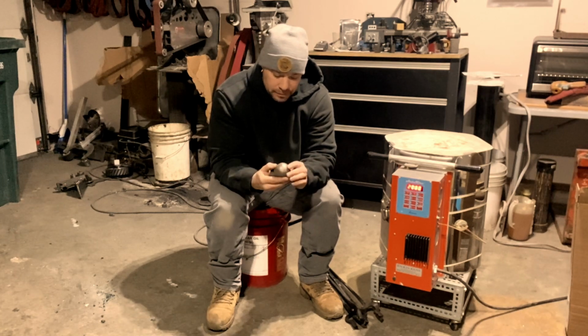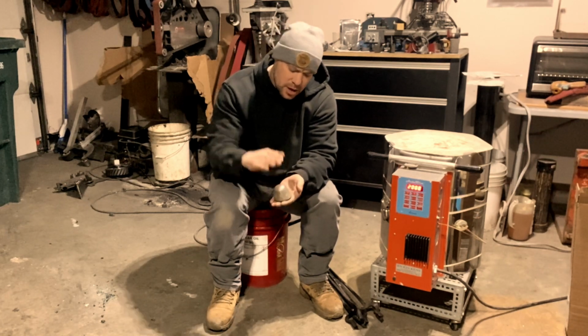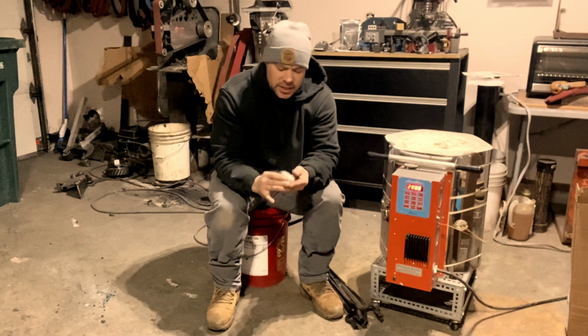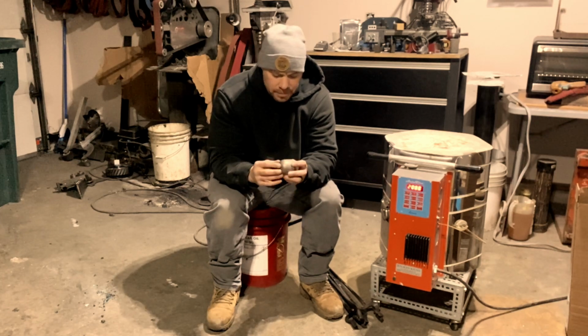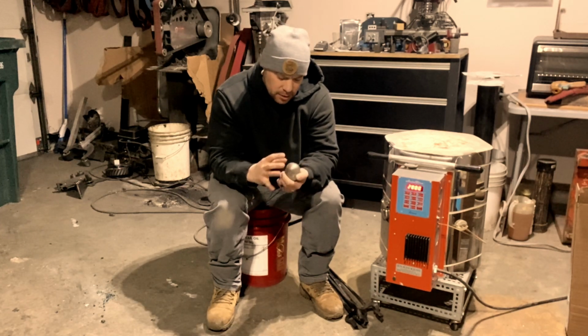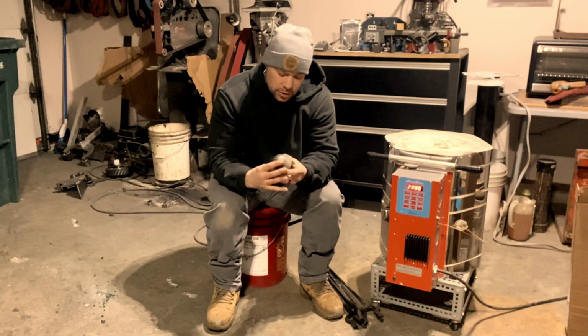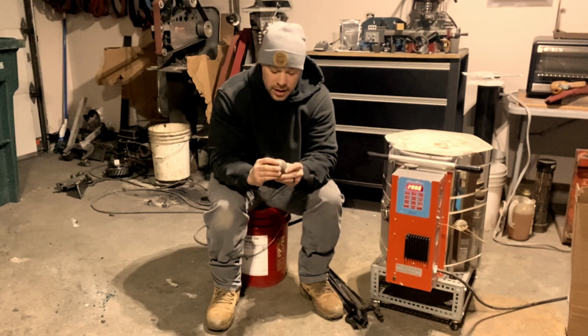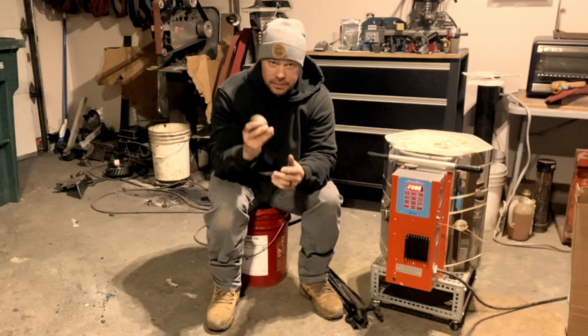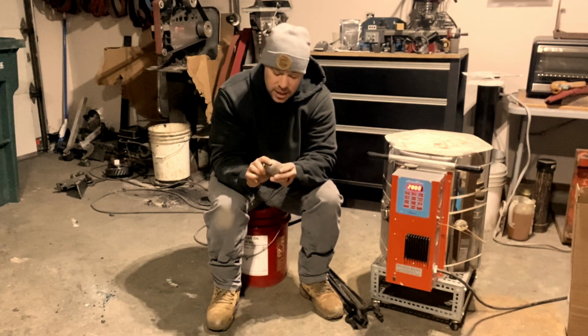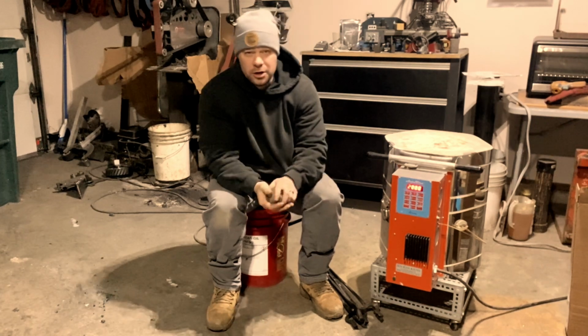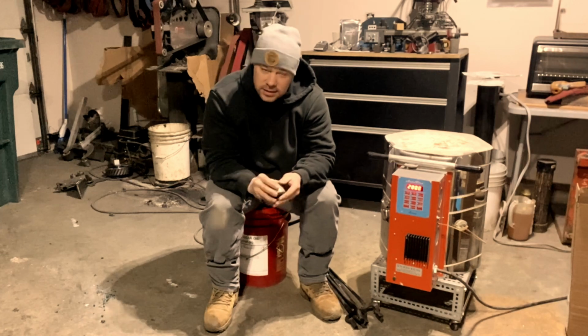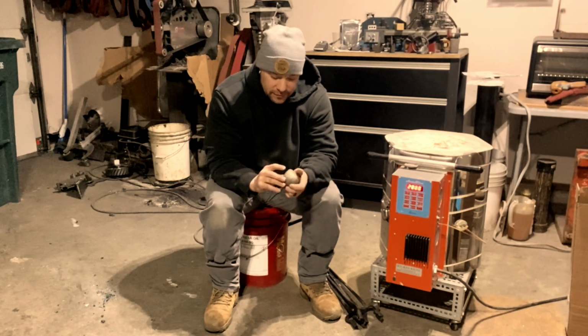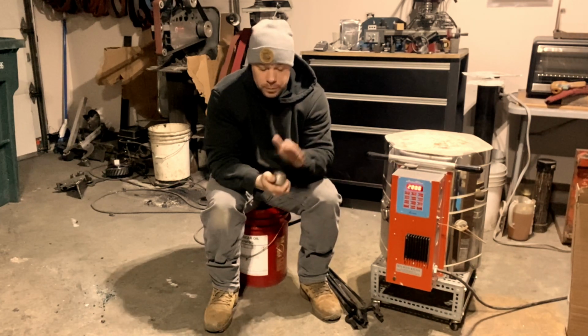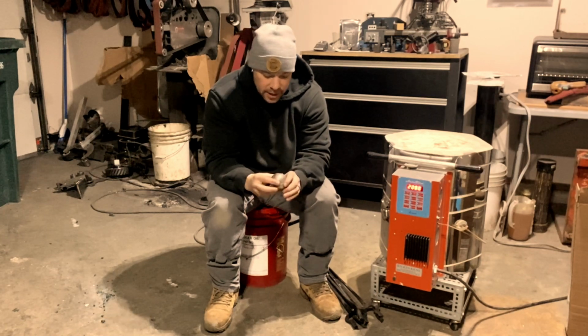And another reason you kind of want to press it down into a biscuit is because if there's any tiny porous holes in the ingot, you want to close those up as fast as possible in the very beginning processes, because there is a chance that graphite can precipitate in those areas, and that's bad. You don't want graphite in there. So we want to close those pores up. So that's what we're going to do.